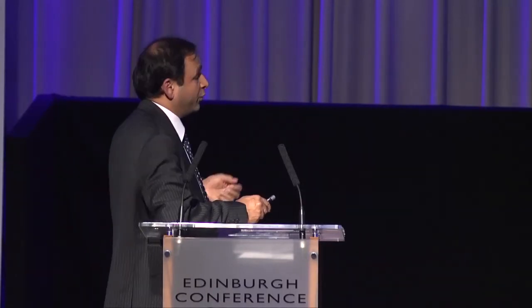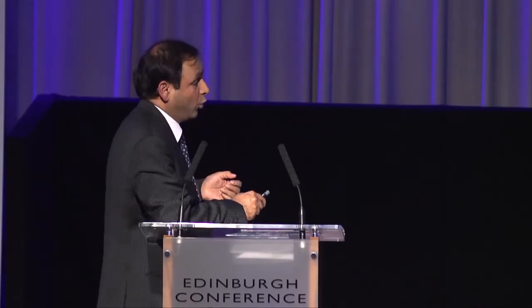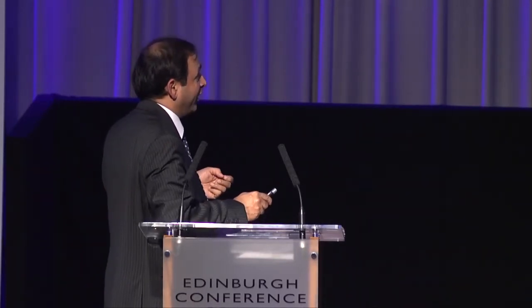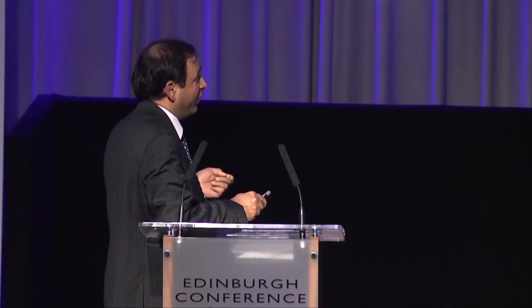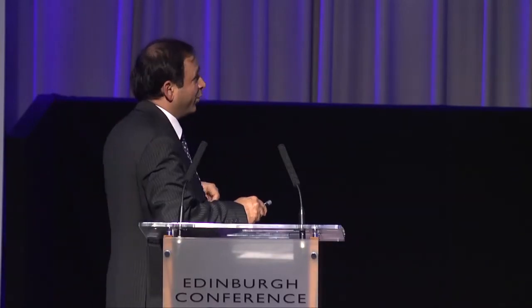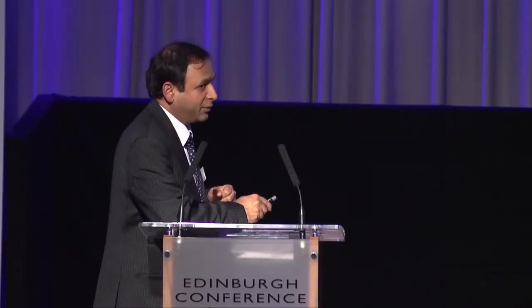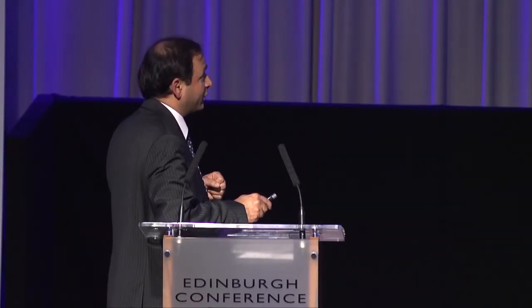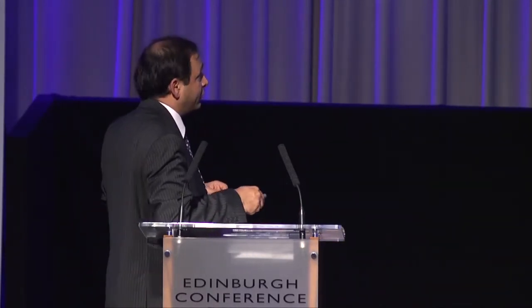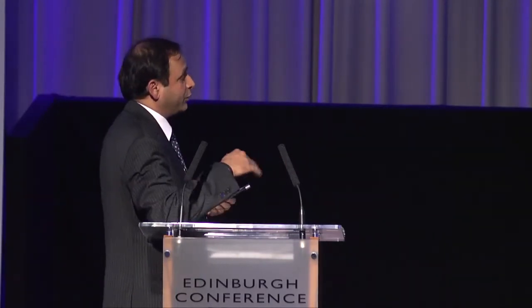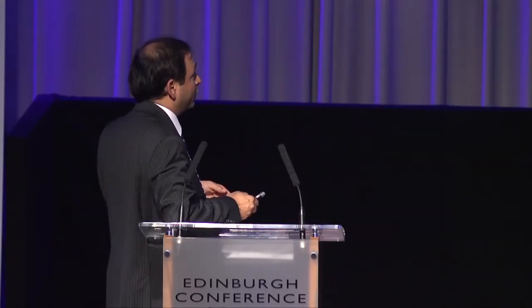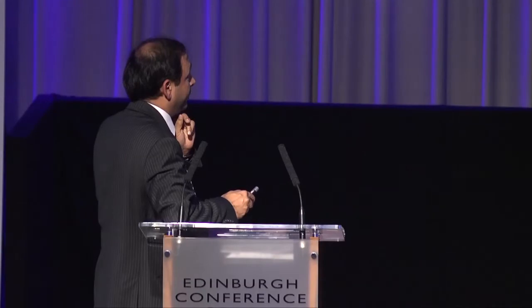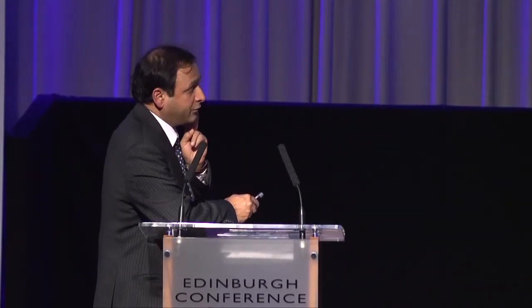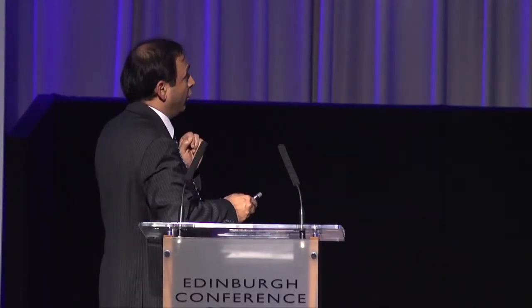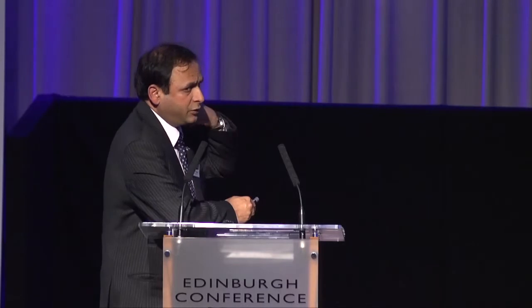The only thing you can see here, what separates it from thin film PV, is that this whole thing is an opaque system. And in order to have light going through to the p-n junction, you have to have some areas which are not covered by metal. So that's where you have shading losses coming from these metal contacts, which are almost like a finger-like structure you will see on the surface. This is not the case in thin film PV, where you have TCOs. For instance, coming to amorphous silicon, you have a glass coated with, say, transparent conducting oxide. This could be AZO, which is aluminum-doped zinc oxide, or FTO, fluorine-doped tin oxide. There are lots of TCOs available.